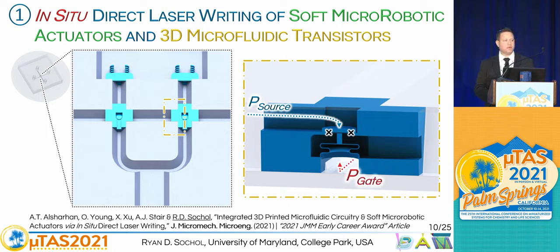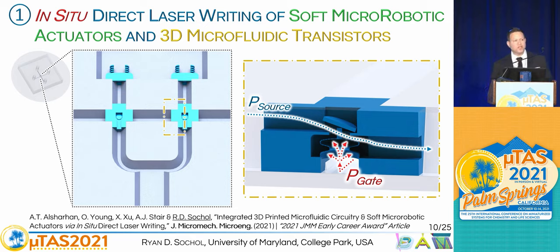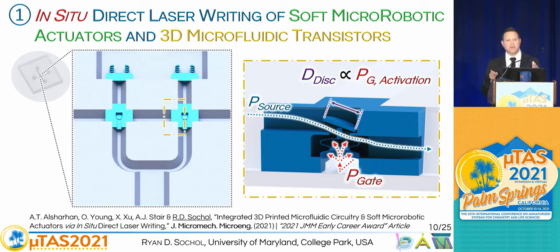But if you apply a gate pressure of sufficient magnitude, it's able to inflate this bellowed microstructure to break that seal, so fluid can now move through the component. And what was really interesting is we found that just by changing the diameter of that disk on top, the larger the diameter, the more force is required to overcome that seal and actually activate the transistor.